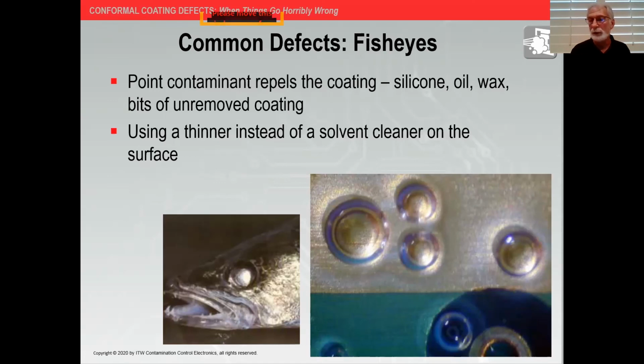And I do want to mention here one thing that I didn't put on the slide, but I've seen this quite a few times. If you're using temporary solder mask in your process to protect areas that you don't want soldered, let's say if it's a peelable mask, once the soldering process is completed and you peel that mask off, there could be a little spot of residue on there that you don't see with the eye. That can be a point contaminant.